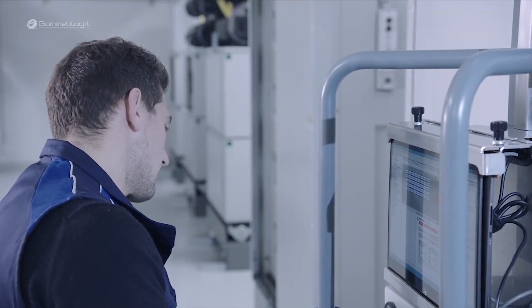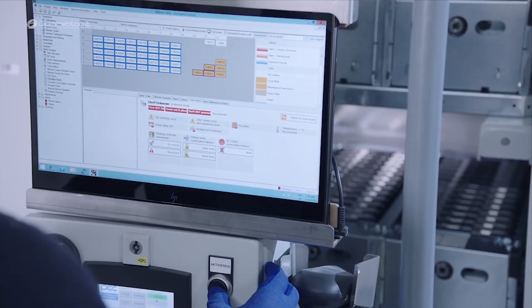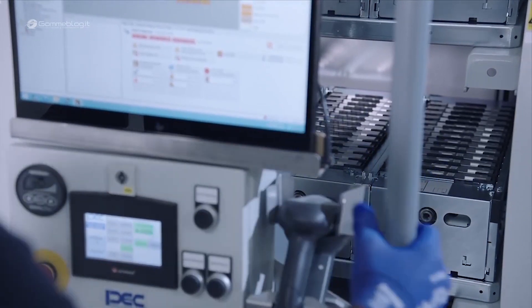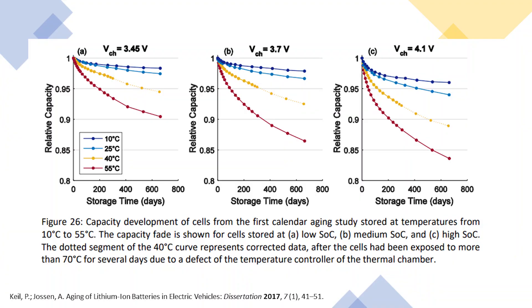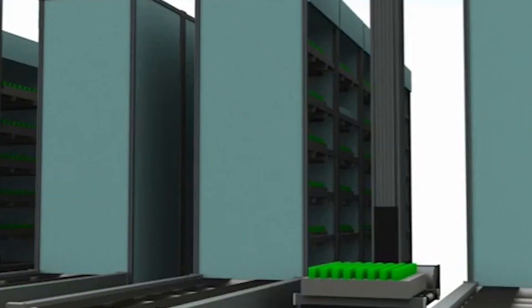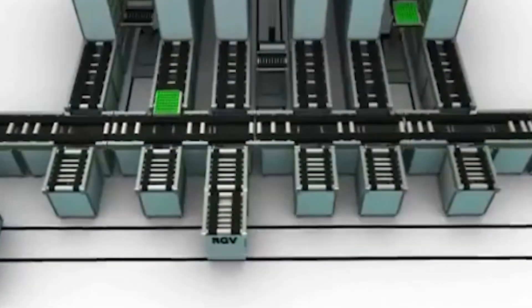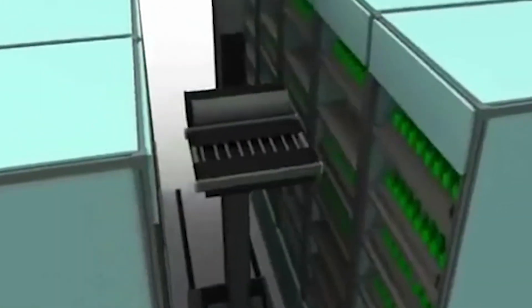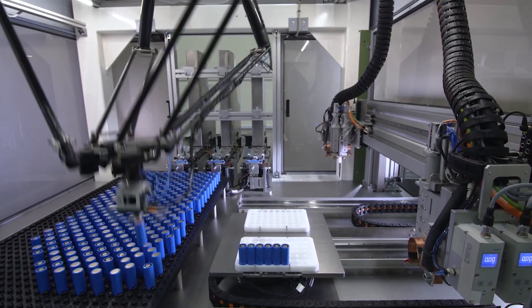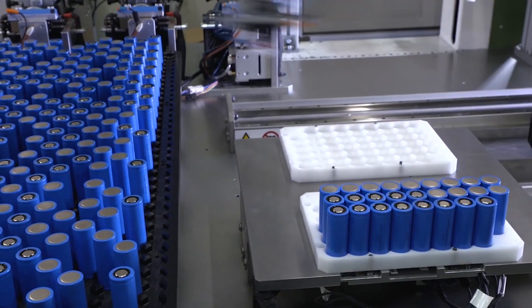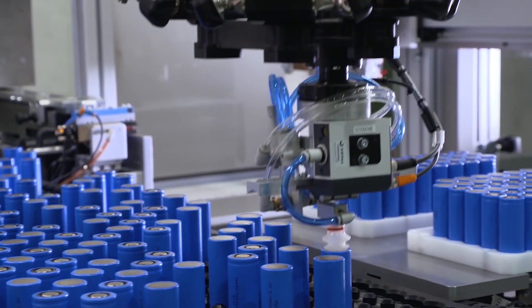After cell formation, these cells are moved to aging towers. During calendar aging we don't apply any current — we monitor the open circuit voltage of the cells. This type of aging depends on the temperature and state of charge of the cells. The aging process first takes place at ambient temperature and then at higher temperatures between 30 to 50 degrees Celsius. The higher temperature ensures the SEI is stable at elevated temperatures and identifies any acceleration in parasitic reactions. A good SEI will have a really low leakage current, whereas an unstable SEI will continue to react and cause parasitic reactions. Depending on the leakage current and additional tests, these cells will be grouped — we call this process binning. Each group consists of cells that perform similarly to each other, ensuring fewer complications in the use application.